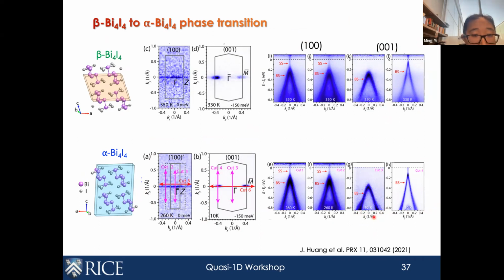If we zoom in, I guess this is the point I should probably mention, that this is where we differ from the earlier report last year showing that the alpha phase of bismuth iodide is topologically trivial with very different fermiology. But here we see that they actually show quite similar Fermi surface topologies between the beta phase and alpha phase. Furthermore, we want to look at what happens to topology.